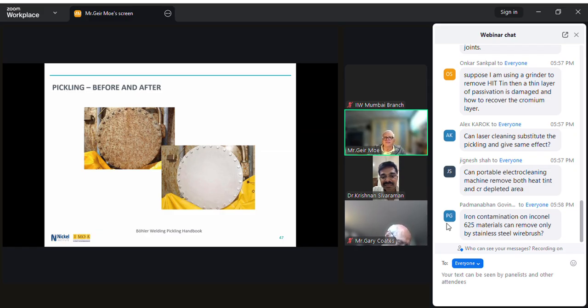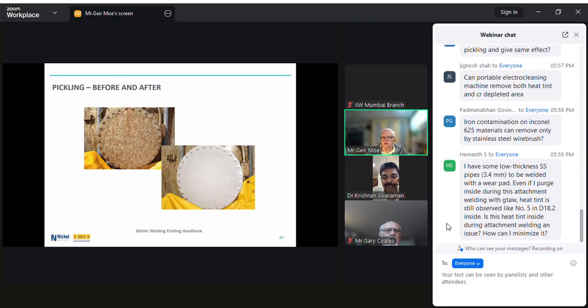So even if you have the heat tint and a chromium depleted layer under it, the base metal will be resistant to pitting corrosion by chloride. So generally, with a nickel alloy, you don't really need to do pickling, but you probably would do it to remove heat tint, primarily for cosmetic reasons.